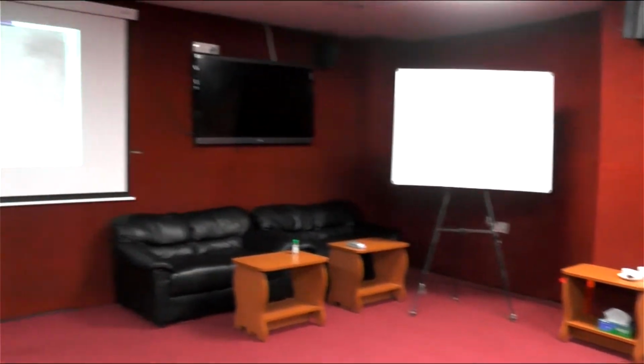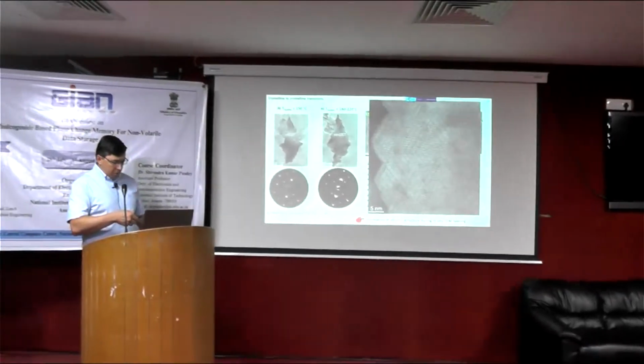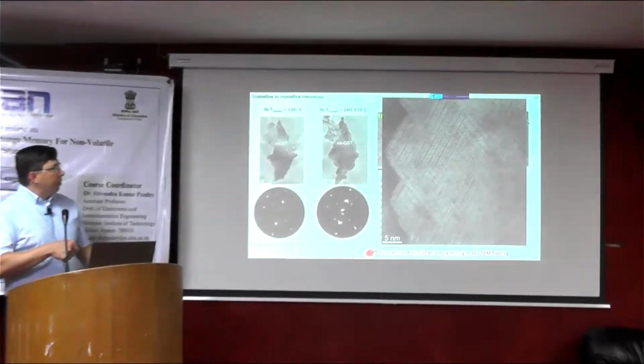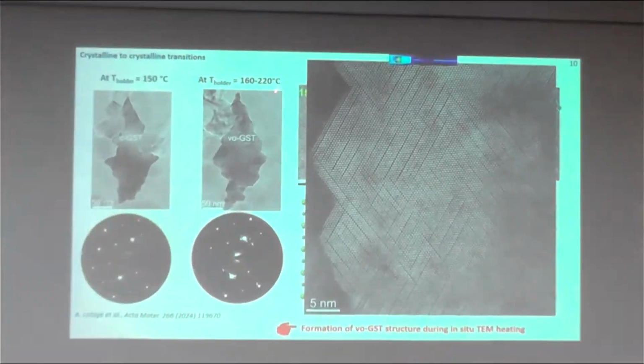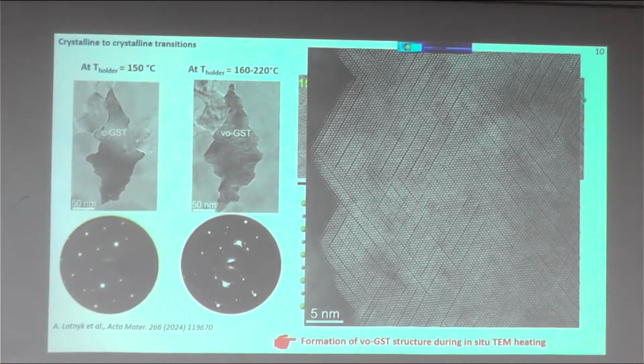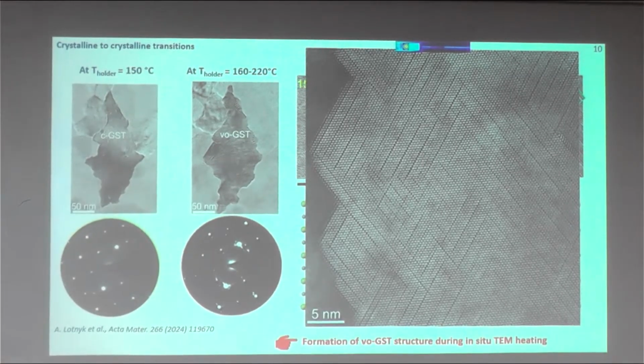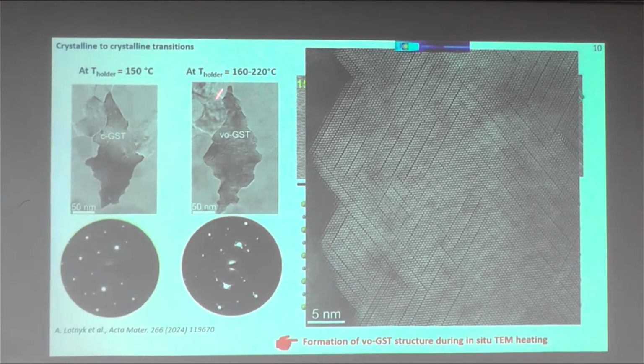Yeah, it's a little bit composition sensitive. For GST 225, because we can create a stoichiometric GST 225, we use in situ heating, but we also compared with ex situ heating, and this vacancy ordering really occurs in this temperature range.